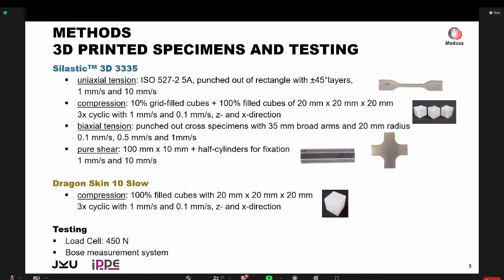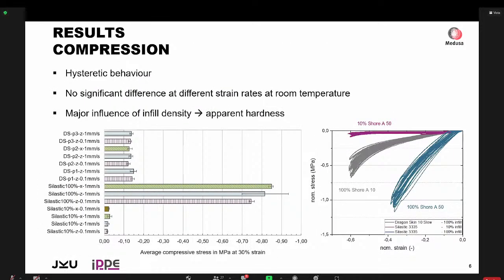And we printed specimens for uniaxial tension, for compression, for biaxial tension, and for pure shear. And for the Dragon Skin material, we printed the cubes also for compression tests. I will only show now the compression test results because those are nicely to be given in an overview. The main thing that we found is that when we have the 100% filled cubes printed with this Silastic, with the Shore A50 silicone. So here we have 100% filled and 10% filled specimen. So we see a lot of difference in the compression behavior. And here in between, in gray, we have silicone elastomer with the Shore A10. So this is the Dragon Skin material.